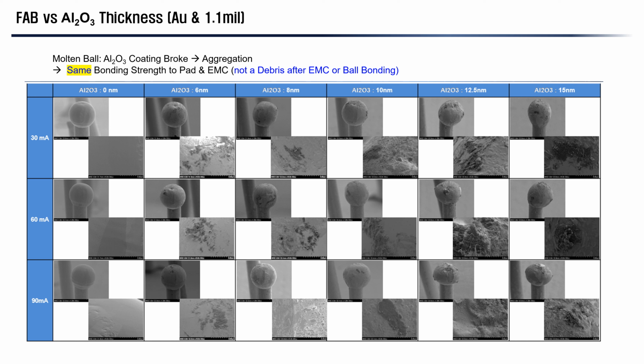On this slide, you're seeing free air balls for aluminum oxide thickness from 0.6 all the way up to 15 nanometer on a 1.1 mil diameter gold wire. The bond wire was melted to form a free ball and it solidified, and you can see the aggregation of aluminum oxide on the ball because the wire was molten but the aluminum oxide was not. The melting point of aluminum oxide is greater than 2000 degrees C. However, I want to emphasize this aggregation is not dirt or contamination of any kind, because this aggregated aluminum oxide can make a good bonding with EMC resin and in ball bonding. So it does not make any degradation in terms of strength.